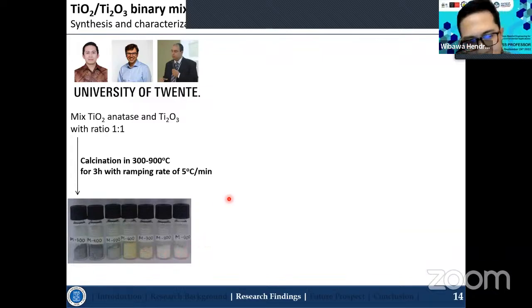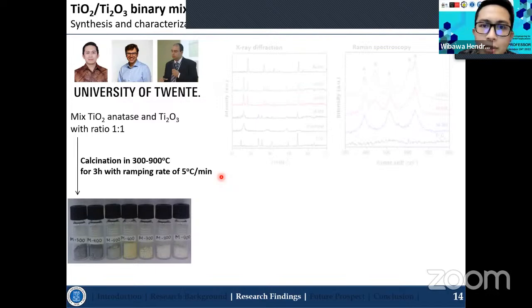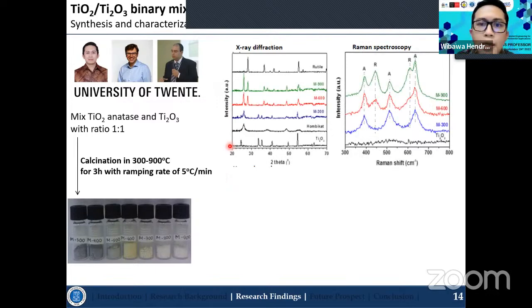So by looking at this visual appearance of the catalyst, we try to characterize this catalyst by using several instruments. For the X-ray diffractions, it can be seen that the catalyst calcined at 300 is still in the anatase phase, whereas at 600 degrees there is a transformation of the crystal phase structure from anatase to rutile, which gradually increased from 600 to 900. There are mixtures between the crystal phases of the anatase and rutile.